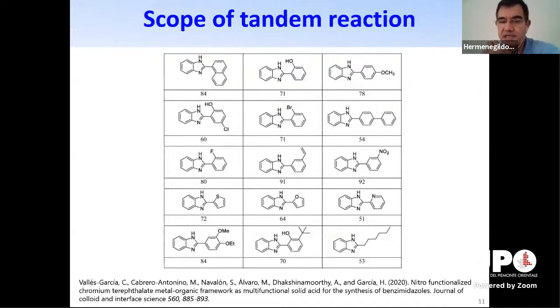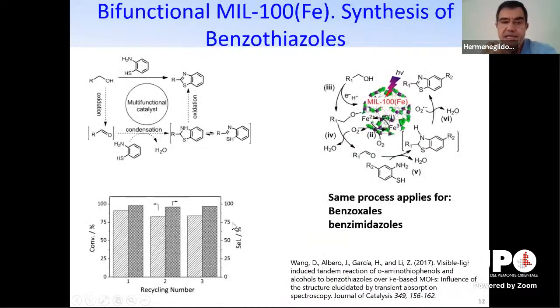This reaction can be done with a lot of benzimidazoles, including fused benzaldehydes, or those having different substituents, electron donors, electron acceptors, even heterocycles like pyridine that typically doesn't work with conventional Lewis acids, and also other heterocycles like sulfur, but also aliphatic aldehydes. So this material works well with a very broad scope, making the tandem reaction.